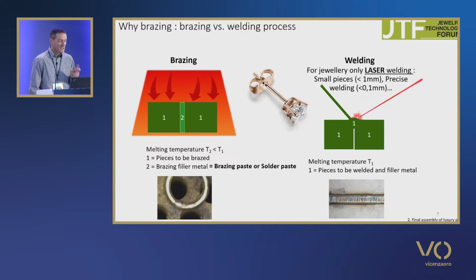I just insist on a wording. What we have to say is, solder paste or brazing paste? According to the standard, the term soldering, also called soft brazing, must be used for assembling with filler metal at a temperature under 450 degrees. For instance, when using tin-based filler metal for assembling electronic components, it is called soldering, and so the filler metal is called solder paste. The term brazing, also called hard brazing, must be used when the assembly is carried out at a temperature upper 450 degrees. It is always the case for luxury goods. Subsequently, only the term brazing paste will be used.